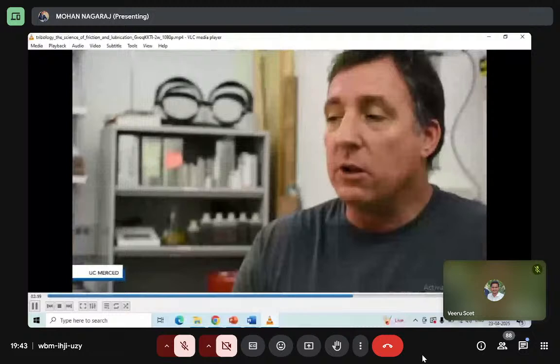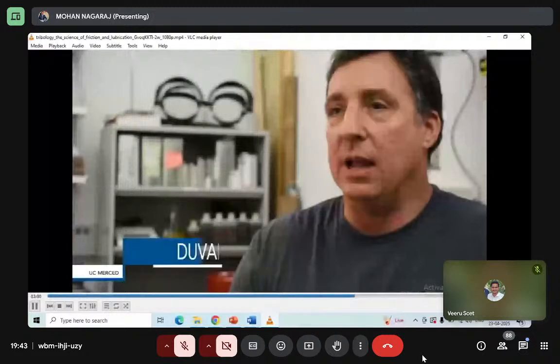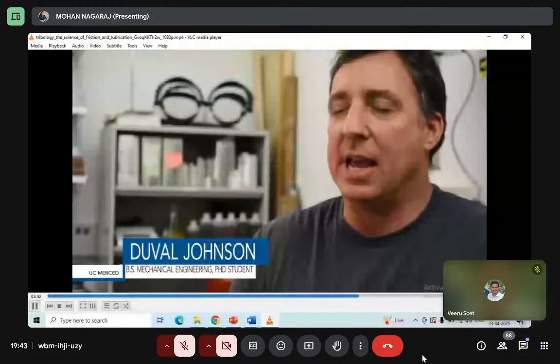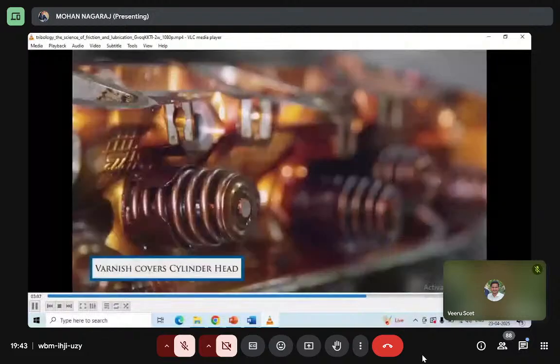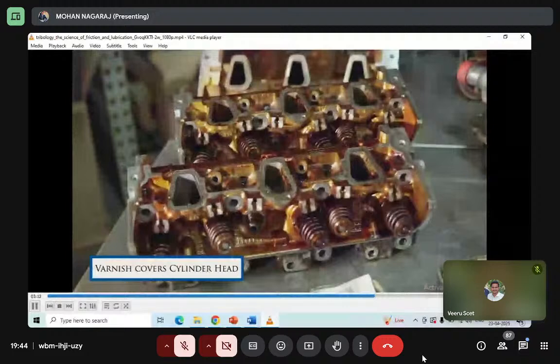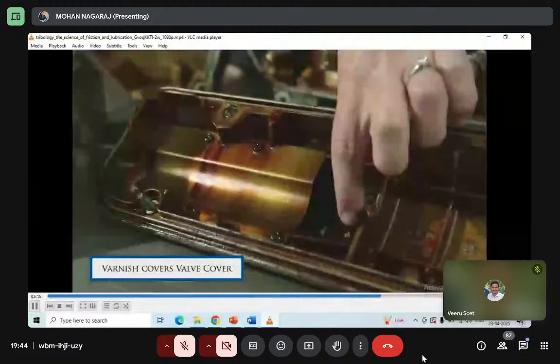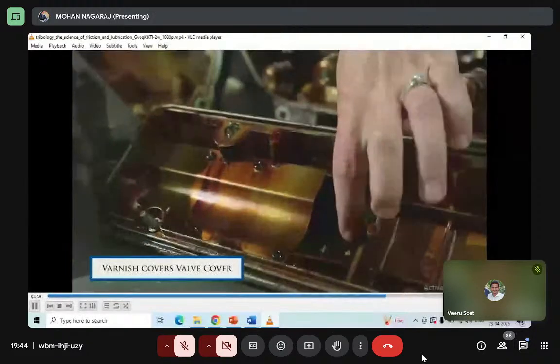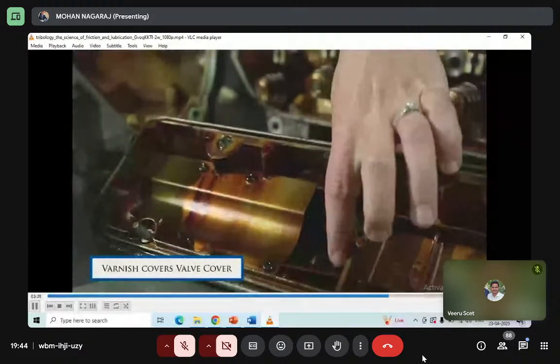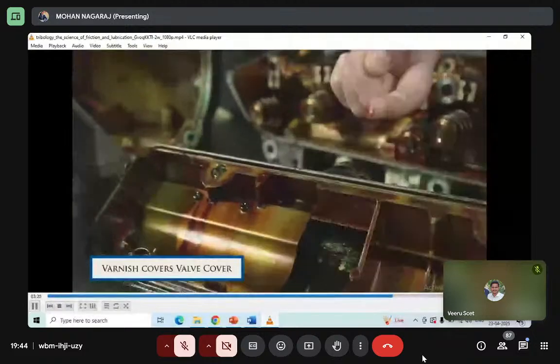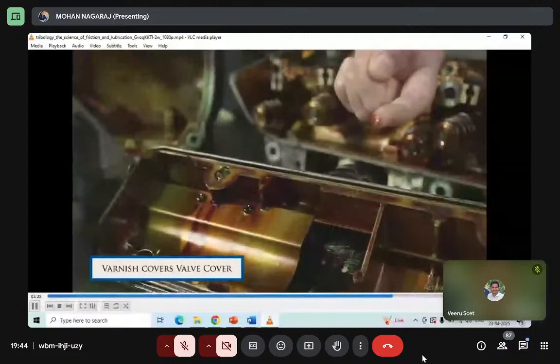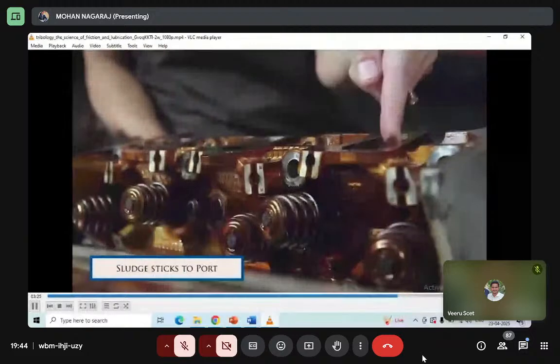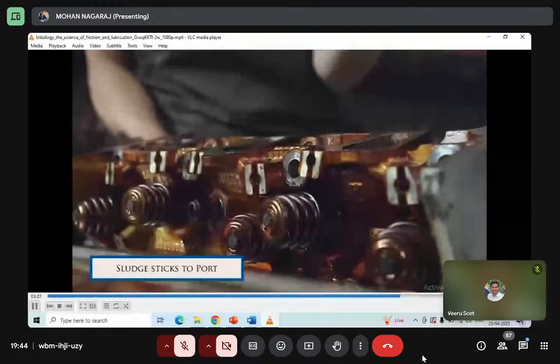Oil degrades, and one of the main degradation channels is oxidation. This is a problem across every industry, the transportation industry and the power generation industry. We artificially degrade oil on the steel component. We take this steel component and expose it to differing chemicals and environmental conditions, like temperature and flow rates, to see if we can remove the varnish.